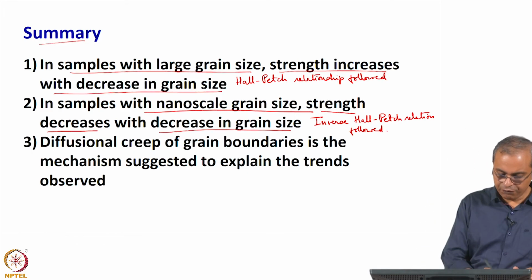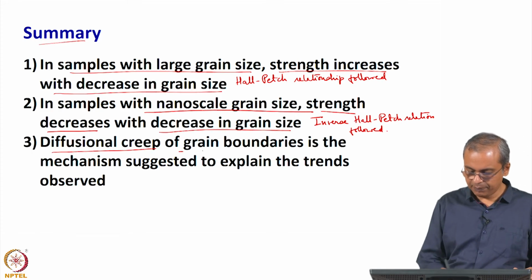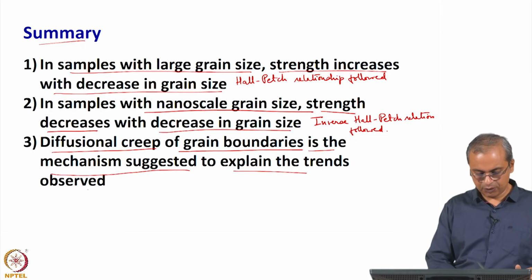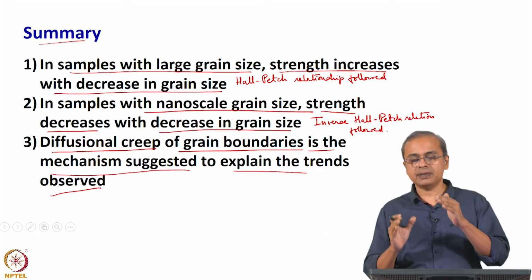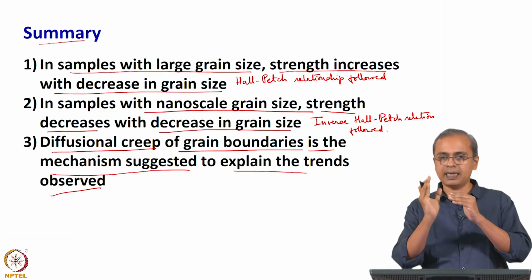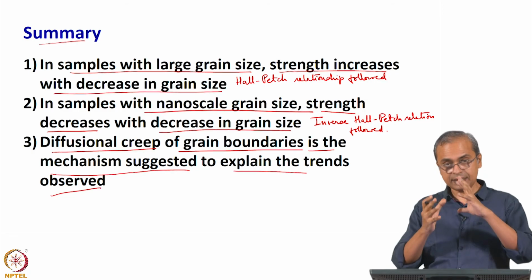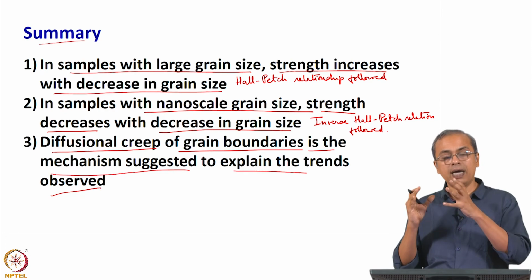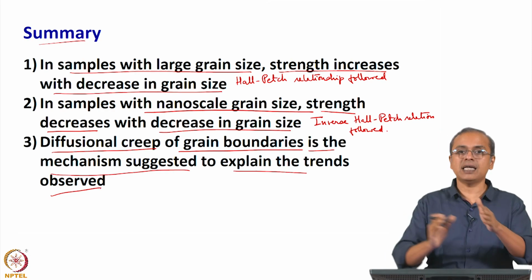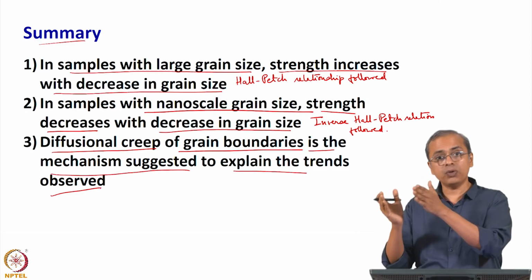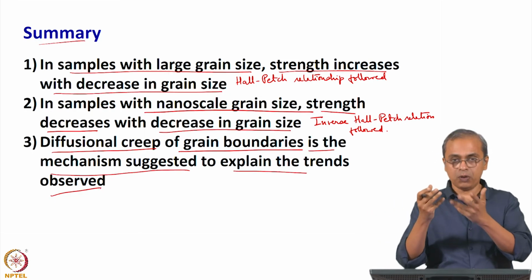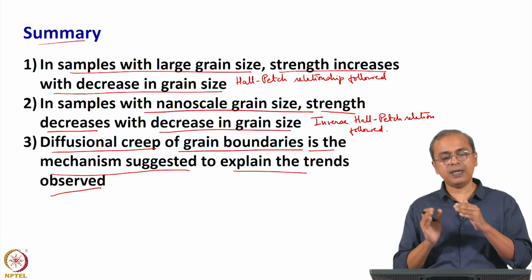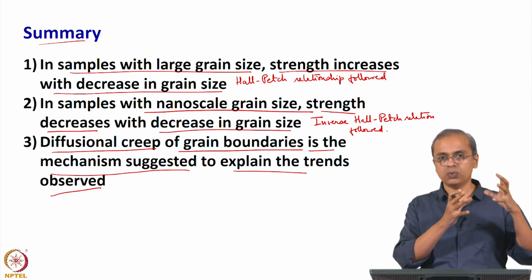Diffusional creep at the grain boundaries is the mechanism that is suggested to explain the trends that are observed. So, this diffusional creep is the creep of vacancies and atoms along the grain boundary. Diffusional creep is occurring due to movement of atoms and vacancies along the grain boundary. Atoms and vacancies can move through the grain as well as through the grain boundary. Generally, there are more defects at the grain boundary because there are incomplete bonds. Therefore, the movement of atoms along the grain boundary is typically faster than it is through the grain.